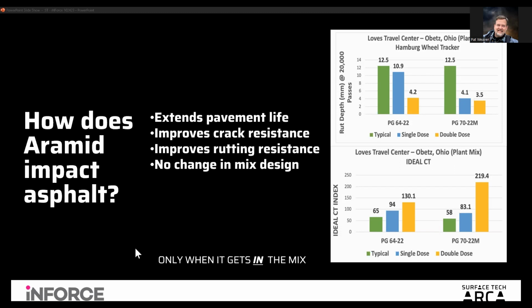Now, conversely, on the crack resistance, it goes through the roof. You see just a single dose in a neat binder here is a 50% improvement in crack resistance right off the bat. And a double dose is a 2 times, a 2x value. And then you add the polymer modified, again, you get the big bump with the single dose and then a really large bump with a double dose. We're going to go in about 20 slides from now, we're going to talk about that more. How eventually the polymer modification wears off over time, but the fiber doesn't. Pretty neat results coming up in one of our case studies we'll share in a few minutes.